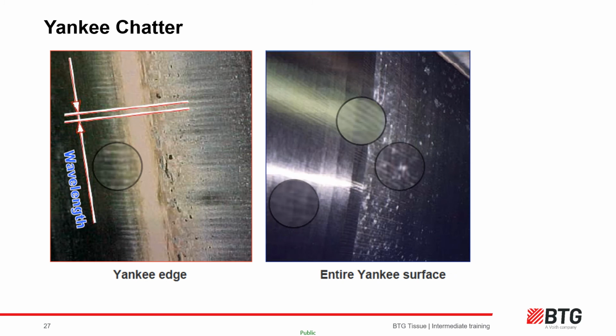Here are two examples of what we don't want to see on a Yankee cylinder. Edge chatter on the left and full width chatter on the right. By measuring the wavelength of the chatter marks and knowing the speed of the Yankee, the frequency of chatter can be calculated and related back to events. For example, edge related issues, full coating related issues or higher frequency rather, or mechanically induced chatter marks at low vibration frequency.